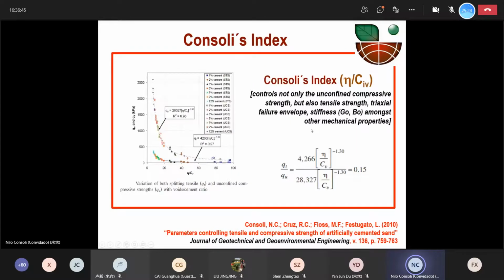In 2010, experimentally, we have shown that if you do test unconfined compressive strength or splitting tensile strength, so if you check compression and tension in this case, both varying the amount of cement and also the void ratio or the dry density, and showing these results with all these amounts of cement and different dry densities, you get unique curves, one for unconfined compressive strength, for example, and another for splitting tensile strength.